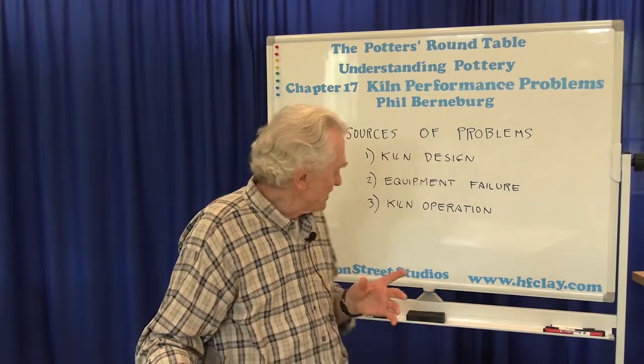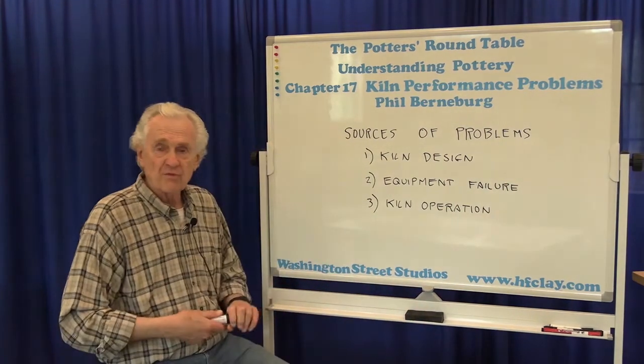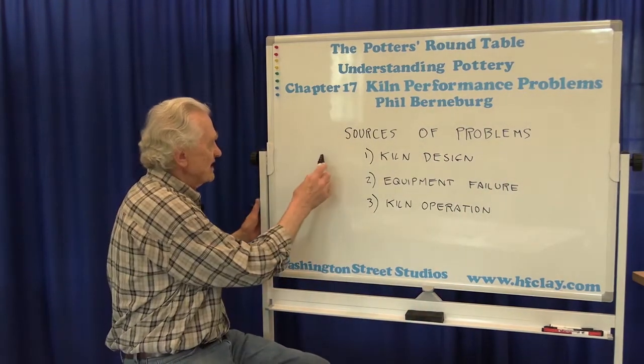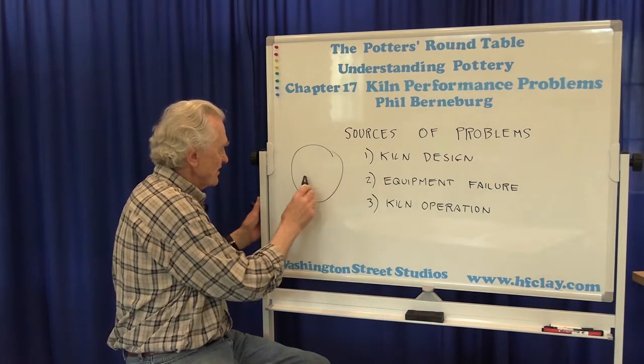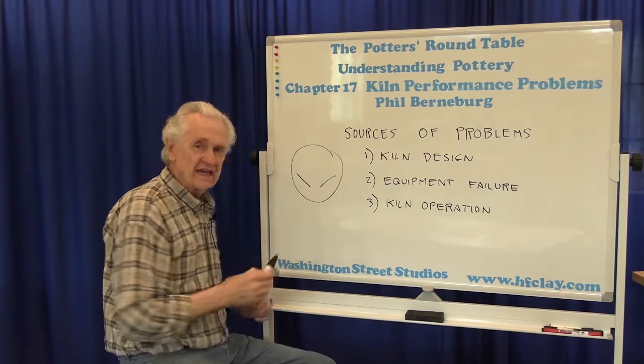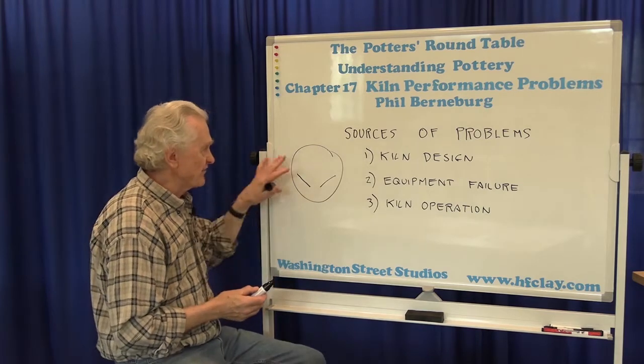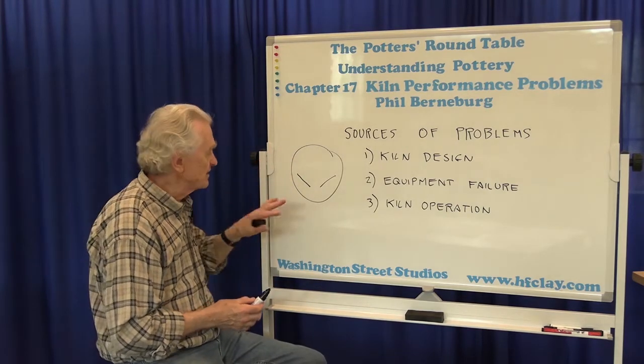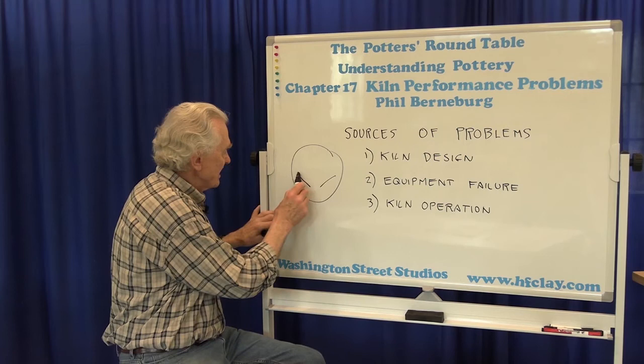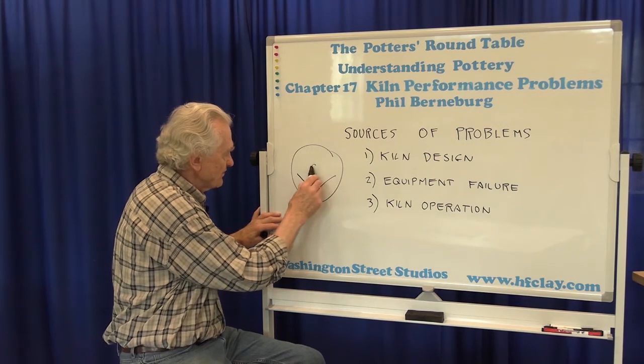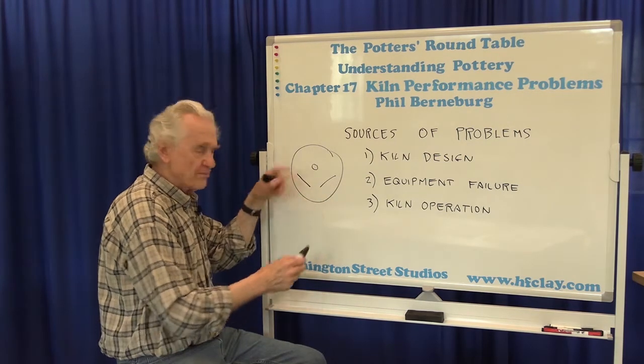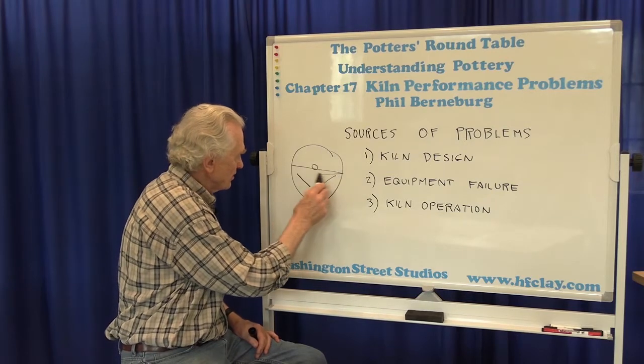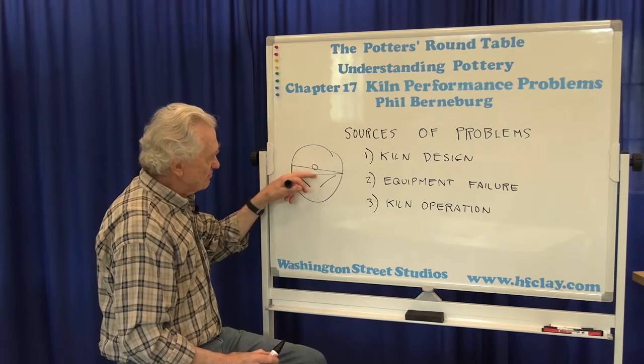And one of the problems that can happen, I'll draw a little something on the board here, is that when you look at the end of the kiln sitter, there are two blades that stick out from the end. This is the ceramic tube that projects into the kiln. There are two ceramic blades, and the cone, and then there's this movable rod that moves up and down, and you set the cone across the blades like that, and then it bends, it moves down.